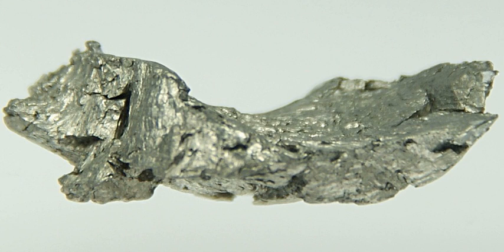The remaining solution is treated with ammonium oxalate to convert rare earths into their insoluble oxalates. The oxalates are converted to oxides by heating. The oxides are dissolved in nitric acid that excludes one of the main components, cerium, whose oxide is insoluble in HNO3. The solution is treated with magnesium nitrate to produce a crystallized mixture of double salts of gadolinium, samarium and europium. The salts are separated by ion exchange chromatography. The rare earth ions are then selectively washed out by a suitable complexing agent.